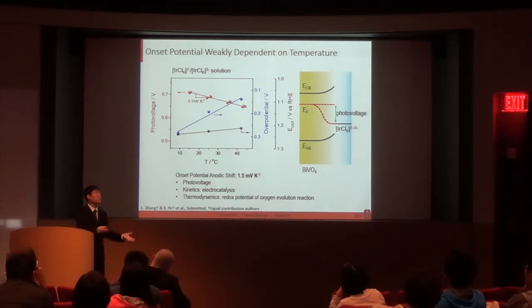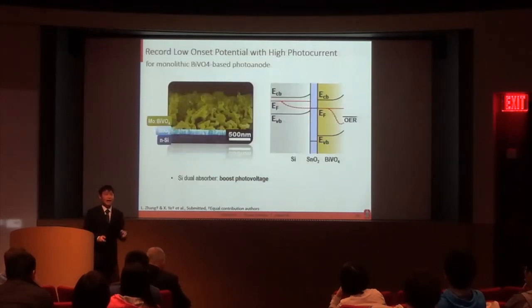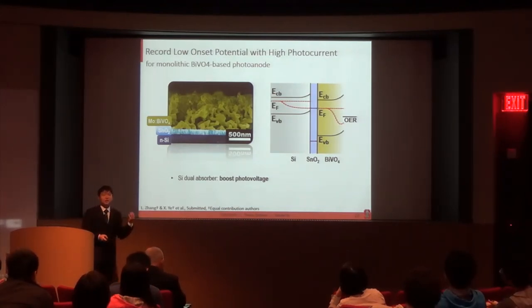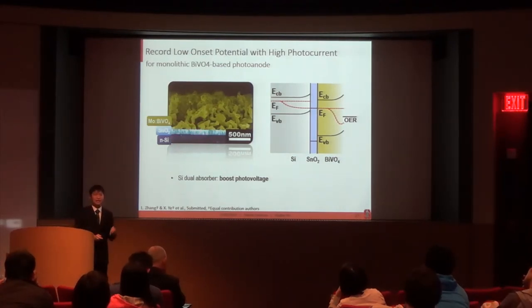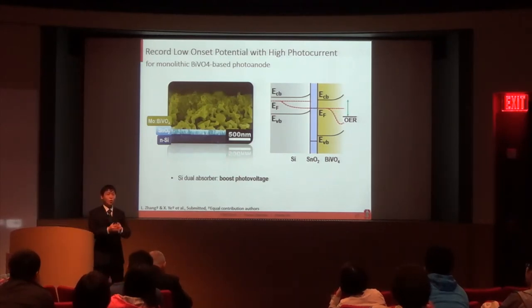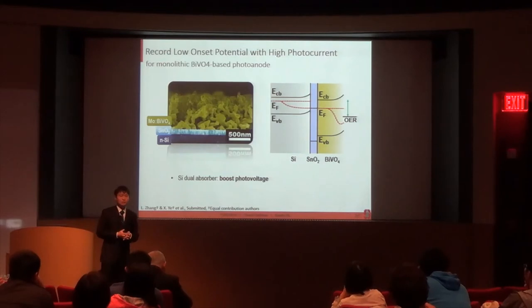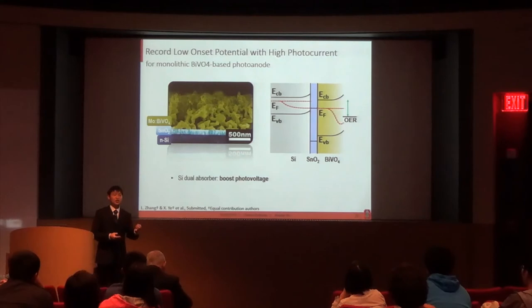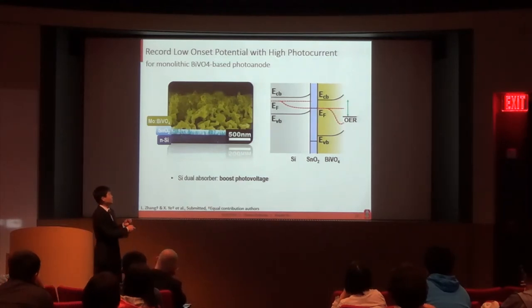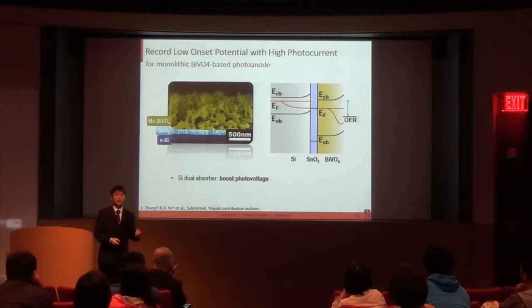In order to further compensate this photovoltage loss, we added a silicon to the backside of the BVO to boost the photovoltage. And this is fabricated in a monolithic way by adding a tin oxide in between as a buffer. As you can see from this band diagram, the tin oxide forms an ohmic contact with BVO, which facilitates the majority carrier transfer, while the tin oxide forms a Schottky junction with silicon, which gives rise to an additional photovoltage. And the total photovoltage is a sum of two.